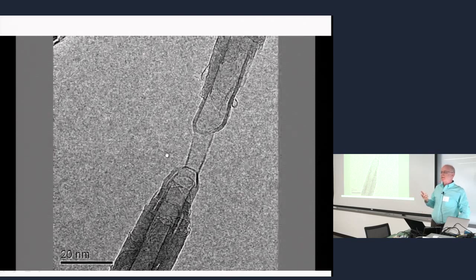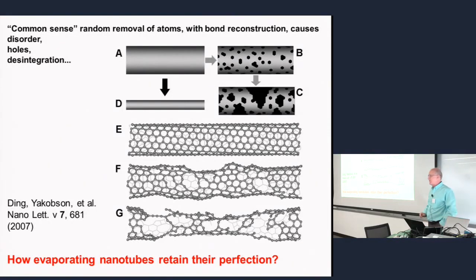It is high temperature plus electron beam. So there is something more, of course, than just plastic glide of dislocations. That's what we explored a little bit because it was very non-obvious. If you think about just using common sense, what should happen? If you have a high energy radiation beam, of course you can knock out atoms and you create defects, probably vacancies or something like this. This is straightforward, and what would you expect? You think that the big structure should become a lot of holes, like a cheese kind of structure, and then fall apart. Why doesn't it do that? Because the experiment shows that it remains pretty much an intact cylinder. It just stretches. You don't see it decomposing into an amorphous, full-of-holes structure.